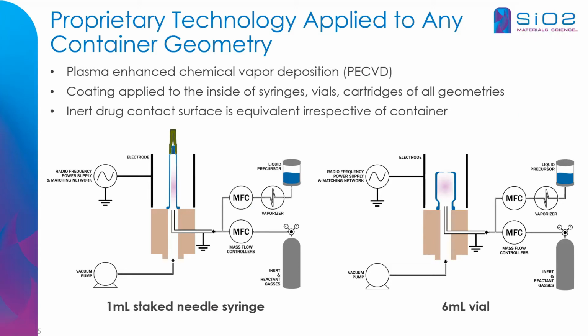The chemistry is identical. Plasma enhanced chemical vapor deposition is a process that really involves three elements. It involves applying a vacuum to the vessel that you want to coat, then delivering a mixture of gases into the container, and then an electric field to actually excite the gases into the plasma state. Now, plasma enhanced chemical vapor deposition is a common way of applying coatings. It's used in many other applications, and it's generally chamber-based, where you put hundreds or thousands of parts in a chamber, pump it down into a vacuum condition, and then apply the gas, which can then apply the coating. In this case, we use the container as the vacuum chamber. We coat them one by one.